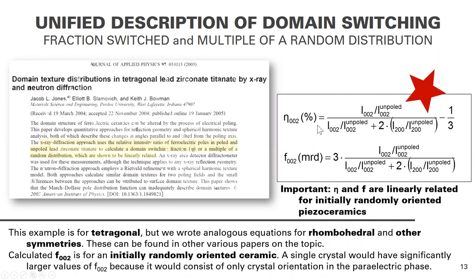So the first two equations in this rabbit hole are shown here. We're not going to derive these today because, again, that could be an hour in and of itself. And so you can go to the paper and you can learn about these derivations. Some important take-home points. These equations use the initial unpolled intensities, which should be comparable in a randomly oriented sample to the powder intensities, or the intensities you take off of a PDF card.